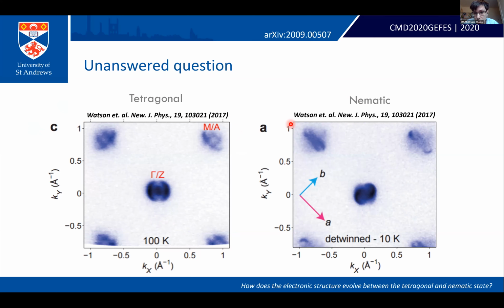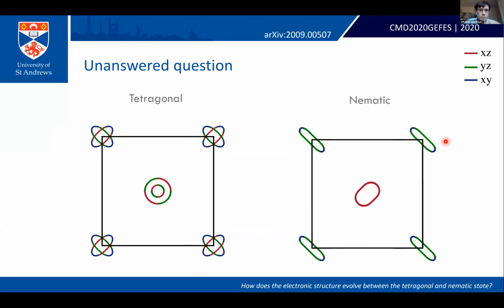And here is the Fermi surface of a detwinned crystal of iron selenide at low temperatures, at 10 Kelvin. So this detwinning simply removes the effect that orthorhombic domains have on ARPES data. This experimental Fermi surface has been reproduced multiple times and is quite consistent with experimental measurements. Here I present a cartoon of that Fermi surface geometry, where these colors represent the maximum orbital content of the bands.